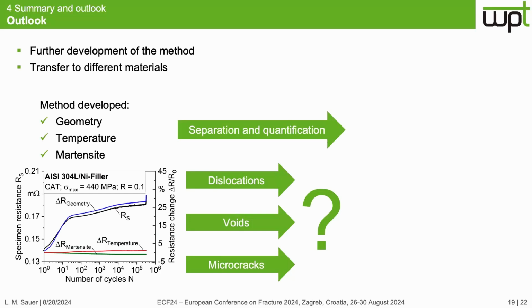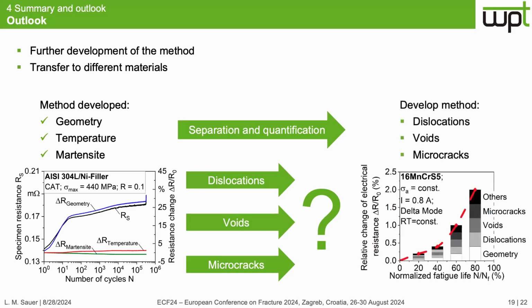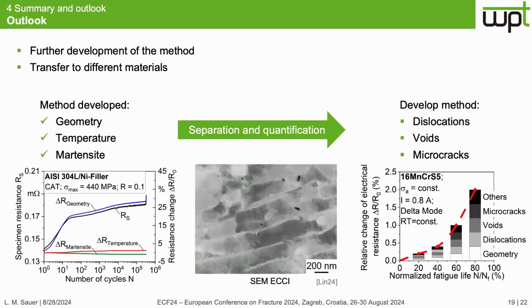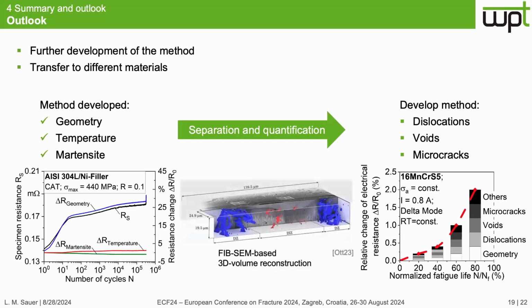the individual influence of dislocation density, voids, and microcracks during the fatigue test, so that the individual influence of dislocations, voids, or microcracks during the fatigue test can be evaluated. And therefore, I'm planning a complex microstructure investigation like SEM ECCI or the use of FIB-SEM-based 3D volume reconstruction models.